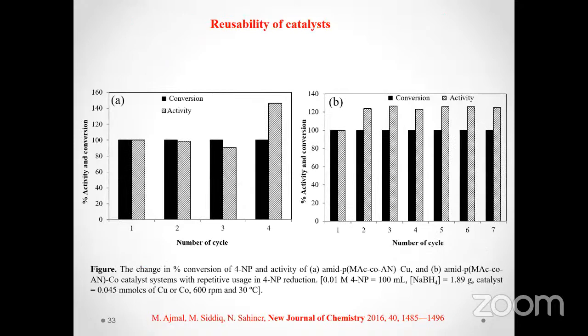And in this case, as I stated earlier, our target was to increase the recycling ability of the system. And we observed that we were able to recycle the cobalt nanoparticle-containing catalyst up to 7 cycles. And even there was no appearance of structural breakdown after the 7th cycle, but due to time constraints, I could go only until the 7th cycle, because every cycle takes almost 1.5 hours, because we have to complete the reaction, then you have to recycle the catalyst. After recycling the catalyst, you need to start the second reaction, and then it goes on again and again for the whole day.